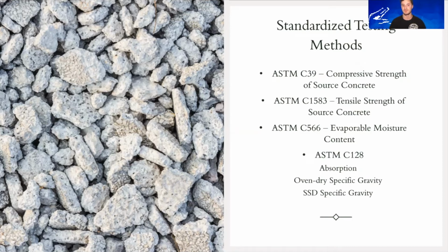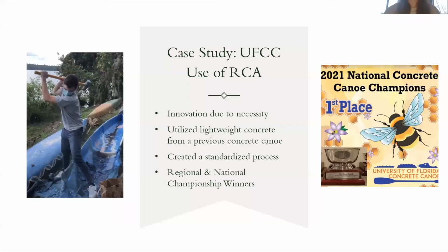These results will be used as a guideline to predict the strength of the RCA based on research, which produces an estimated loss of strength during the RCA production process. Testing data for absorption, oven dry specific gravity, and saturated surface dry specific gravity of the aggregate can be obtained by following the test method prescribed in ASTM C128. The evaporable moisture content of the aggregate was determined by following the procedure outlined in ASTM C566. Other relevant tests on the aggregate can also be performed depending on necessity and use.